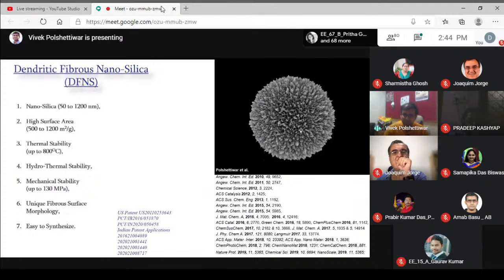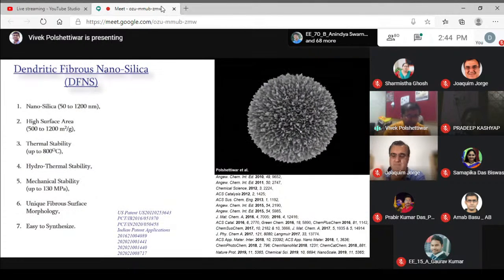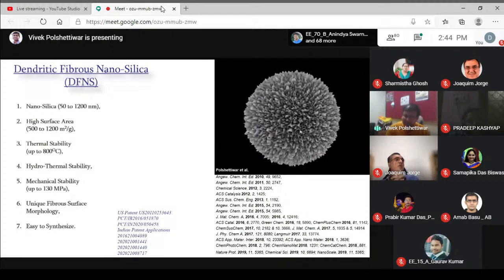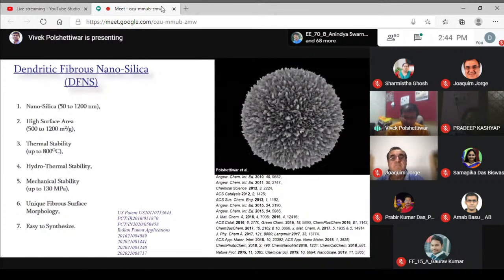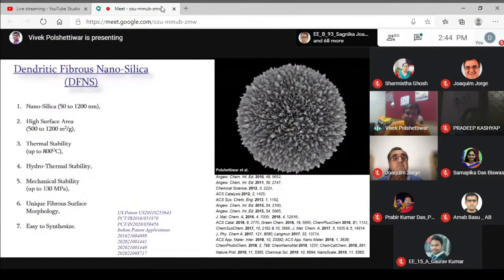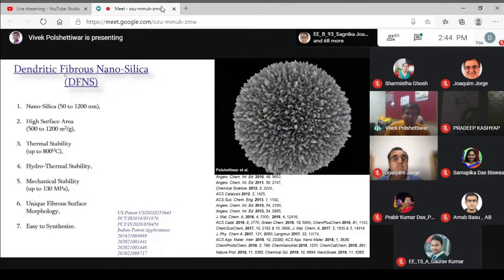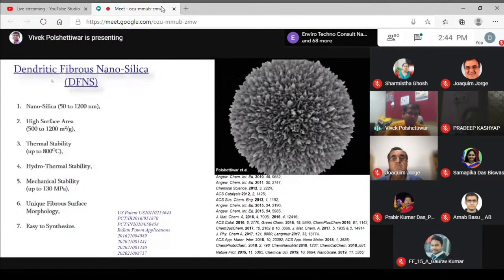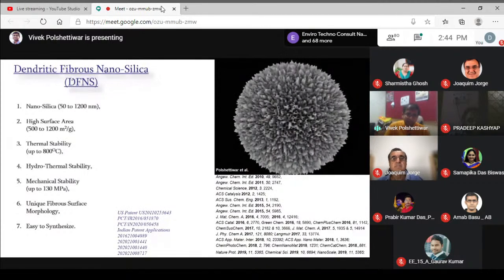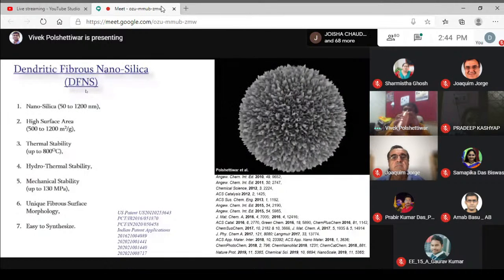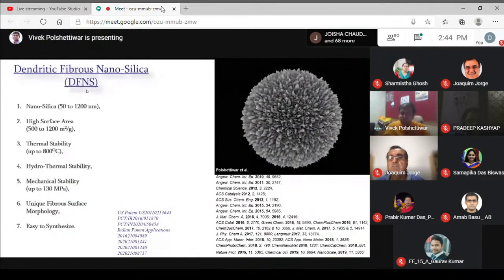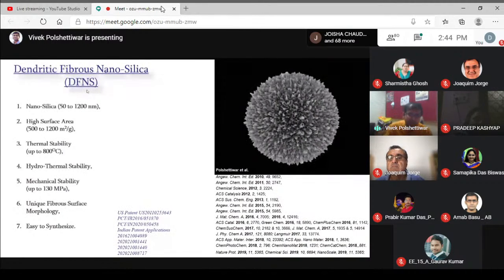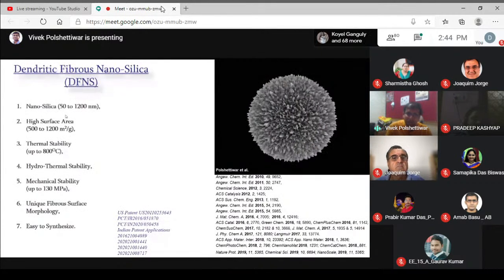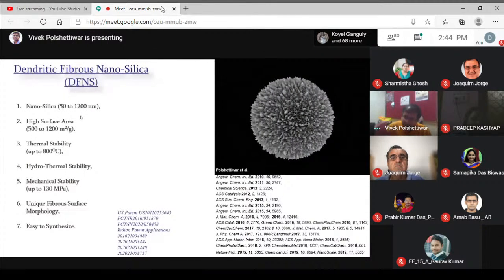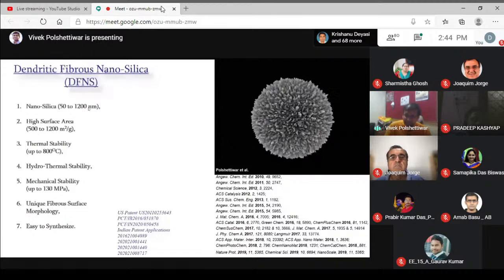So this is the material that we discovered in our lab. This is a pure silica, SiO2. It's like purified sand on the beaches, but it is nanoscale and it has this dendritic fibrous morphology, and that's why we call it a dendritic fibrous nanosilica, a DFNS. We can prepare the nanoparticles from 50 nanometer to 100 to 150, up to 1200 nanometer size.